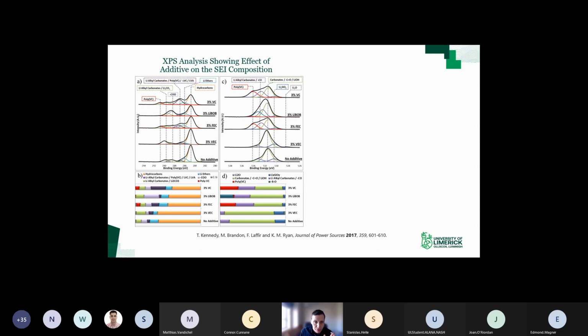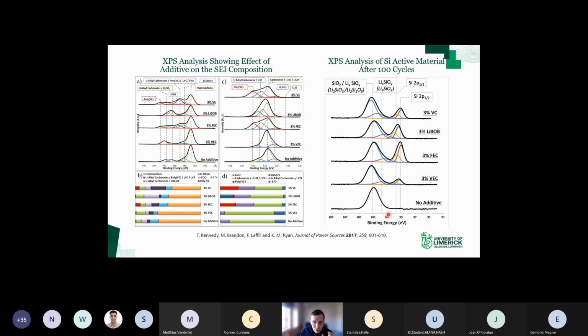This XPS here is of the SEI layer. We also did XPS of the actual active material. So we washed off the SEI layer and just did XPS of the silicon that was left behind. This provided a very interesting result in that when we looked at the no additive material, we actually couldn't even detect elemental silicon. Now XPS is obviously a surface technique, so it probes around 10 nanometers in, but we could not find elemental silicon. So what that told us was that the SEI layer is so unstable that it keeps cracking and recracking. So not only does the SEI layer keep reforming, but when it does so, it actually consumes the silicon.